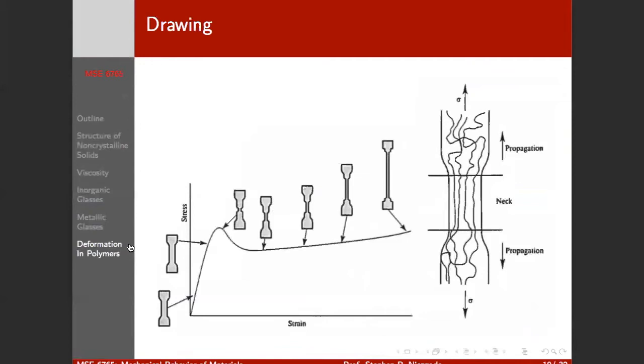Once the neck forms, the deformation is going to happen in that region of softening just outside the neck, rather than inside where it's significantly stronger. And so you basically can propagate your whole sample like this. And this is sort of the example that you do in the project problems. You can demonstrate this pretty clearly for yourself